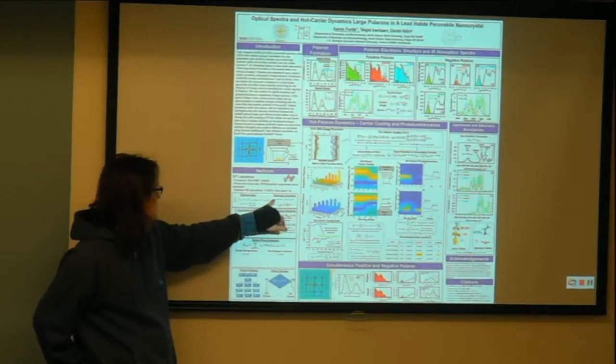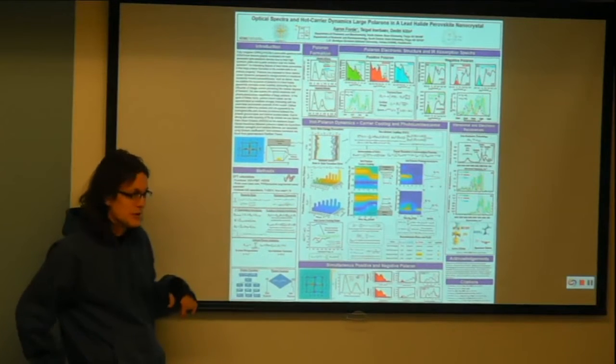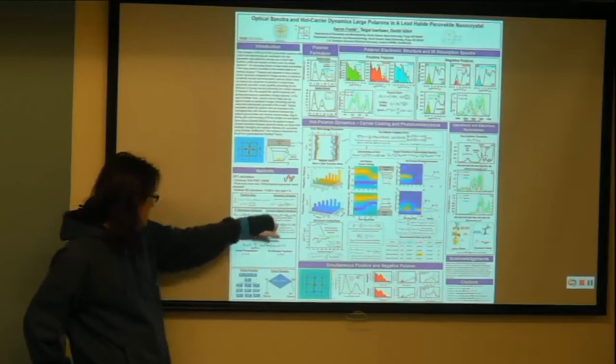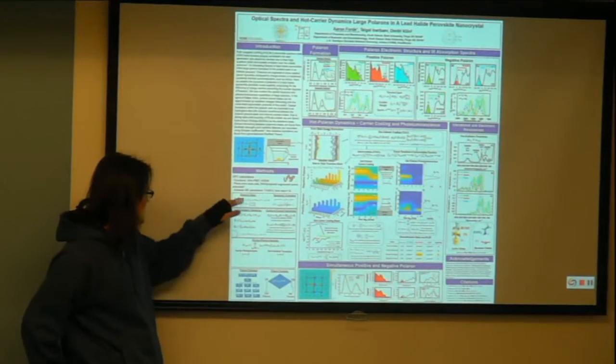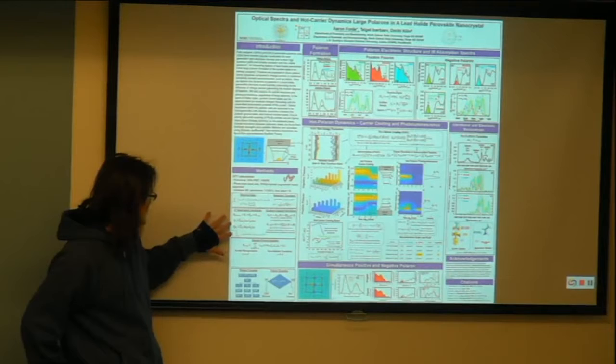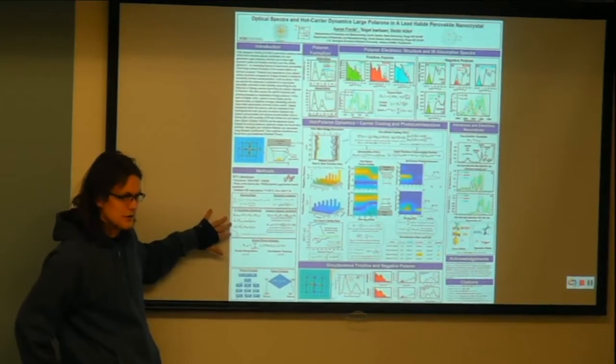Since we're dealing with lead states, or lead p orbitals, we have to include spin-orbit coupling in the calculations. We do that using relativistic corrections. And so this is just an overview of how we compute the polaron states in our atomistic model.